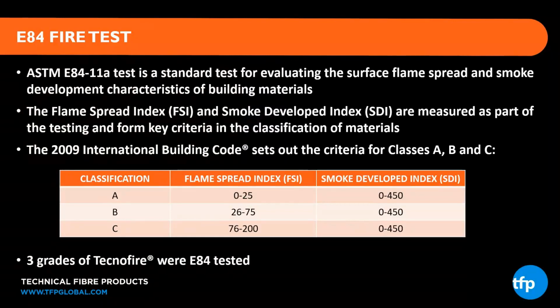The IBC, the International Building Code, classes these into 3: A, B, or C. A is what I found in my experience that most manufacturers are looking to pass. The difference between A, B, and C is the flame spread index. The smoke index, the SDI, will remain consistent. Any SDI above that 450 is considered a non-survivable situation. So we're looking at designing, say, a flat panel or some kind of a composite panel that can achieve a Class A. We've also elevated some other programs where people have passed with a Class C before they want to get to an A. And Tecnofire has enabled that in some cases. We looked at, in this particular test, 3 different grades of Tecnofire. Next slide, please, Neil.